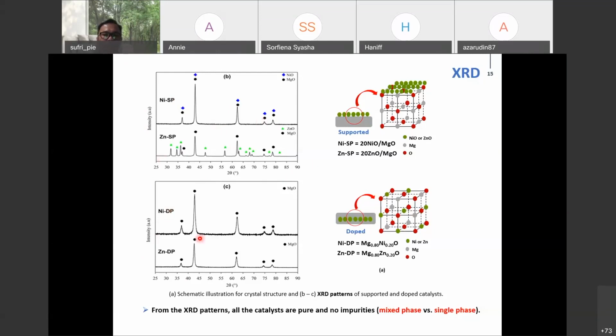As you can see from the XRD diffraction patterns, all the catalysts, nickel SP, zinc SP, nickel DP, zinc DP, exhibited the XRD peaks of magnesium oxide, because each catalyst contains magnesium oxide. So the magnesium oxide should appear in each catalyst. It is indicated by the black dots. This is MgO, MgO, MgO, and so on.